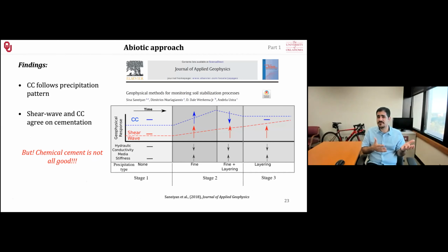Either being the shear wave velocity, which showed an increasing trend over time, no going down, and the complex conductivity that showed the pattern of the precipitation as well. Not just showing that, okay, we have a stabilized soil, but it also showed us when it's the time to stop injecting calcite. We don't need any more material.